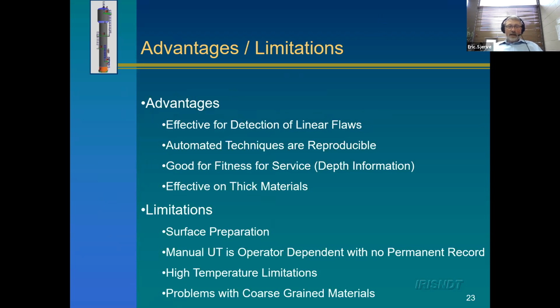The other advantages of ultrasonic inspection are that it's good on thick materials, but it's not so good on thin materials. So when you get to really thick welds, it's what you do 100% of the time. You want to always do ultrasonic inspection. For limitations, you have to do a fair amount of surface preparation before you do ultrasonic inspection because you have to couple the sound in, and that coupling has to be consistent. So you can't be on a bad surface. It's difficult at high temperatures. Like I said, you can't do it well on coarse grain materials like stainless steels or Inconel alloys. And if you do manual UT, you've got no permanent record. So those would be the advantages and limitations of ultrasonic inspection.